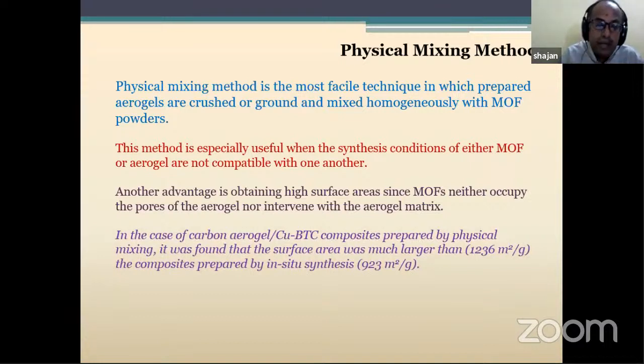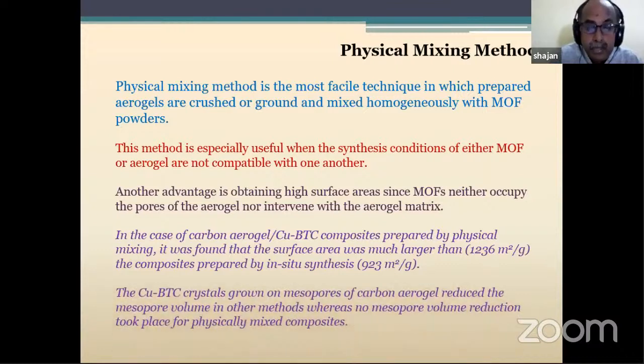One example is carbon aerogel with copper BTC. You are able to get around 1,236 meters squared per gram, whereas the same thing prepared by in situ synthesis gives only 923 meters squared per gram. And the same for the volume: there is no mesopore volume reduction in the physical mixing method.